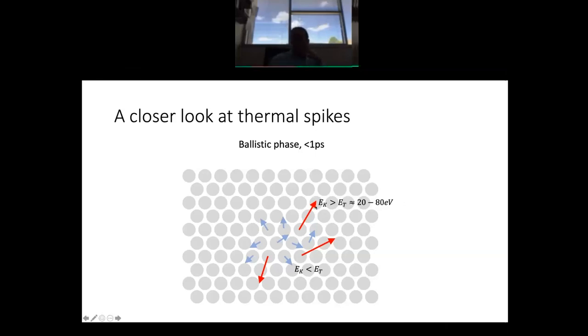So there are going to be a couple of atoms that receive an energy that's above this threshold, and then there's going to be a bunch of other atoms that receive an energy that's below the threshold. Okay, so the atoms that receive the energy above the threshold are going to displace. So for example, let's say I look at this atom right here. It's going to displace far enough away from its original location that it's going to leave behind a vacancy, and it's going to become an interstitial. Okay, and this other atom here is also going to leave behind a vacancy and become an interstitial when it displaces. This arrow that I drew here, if you look closely, is actually aligned with a close packed direction in this particular crystal structure, and that's not accidental.